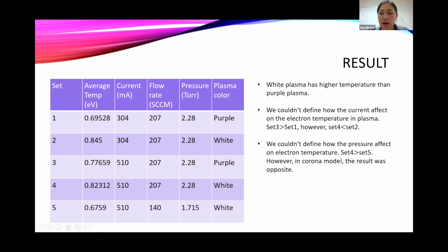However, we couldn't define how the current affect on the electron temperature in plasma. When we compare set 3 and set 1, set 3 has higher current. However, set 3 has higher temperature. However, when we compare set 4 and set 2, set 4 has lower temperature even though set 4 has higher current than set 2. So that's why we couldn't define how the current affect on the electron temperature in this project.